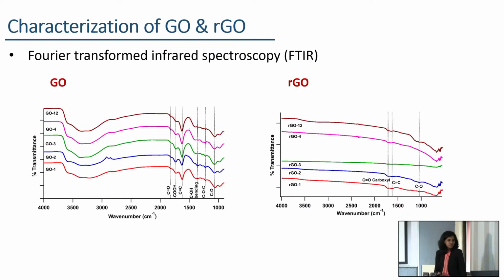When it comes to the FTIR spectra of these GO and RGO, the FTIR spectra of graphene oxide show IR intensities that correspond to different oxygen functionalities. Here we can see the incorporation of hydroxyls, then epoxides, then carboxyls and carbonyls into the graphene oxide during the graphite oxidation process.